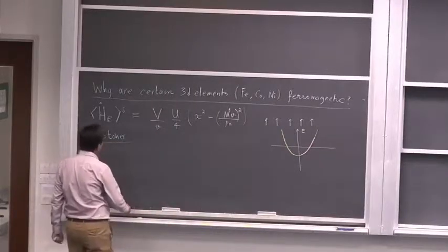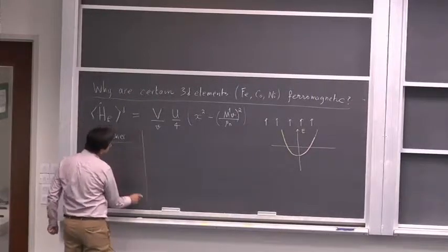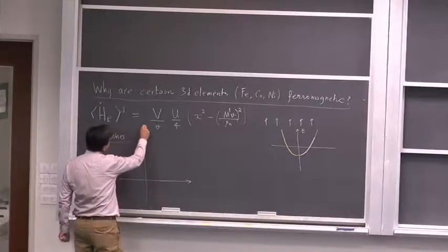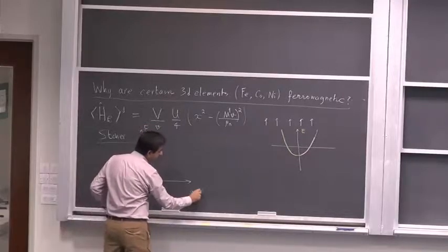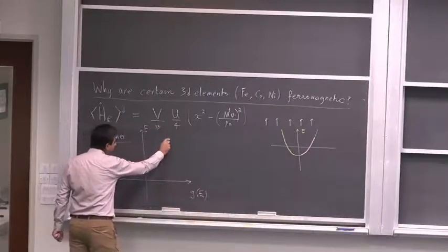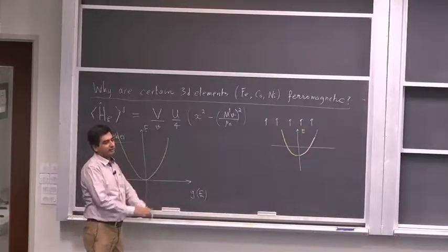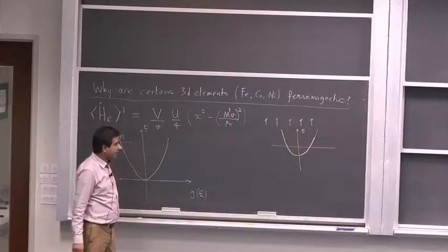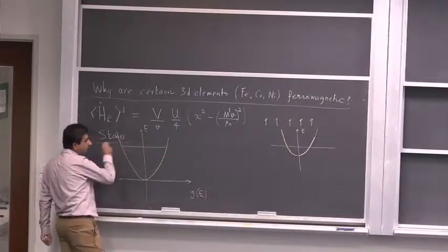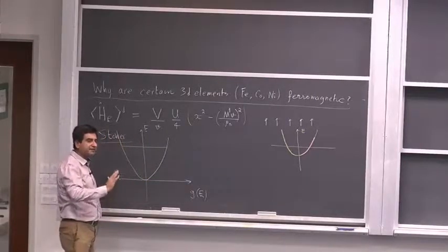So if you look at my lecture number 12, we discussed the concept of Pauli paramagnetism, in which I have the energy on this axis, the density of states here, and if I assume a nice model for the band in which the band is represented by a parabolic curve, then for this particular model I have a certain Fermi level, and I split the bands into two spin split bands, two spin sub-bands.